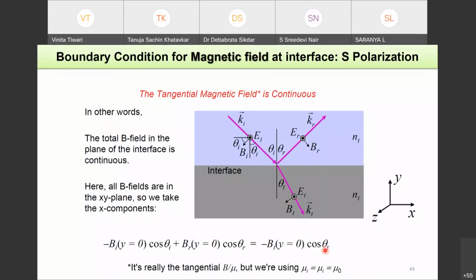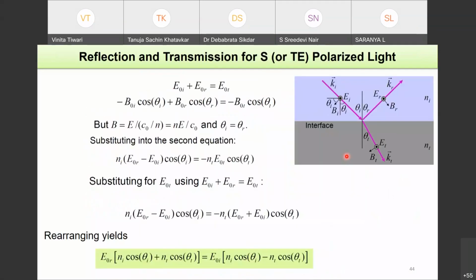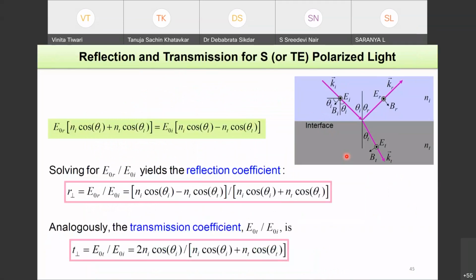And why we are dealing with B, that is the magnetic flux, not the magnetic field, because you can also do it for B by mu. That will be exactly the same, because all the mu's here are 1. We consider all materials as non-magnetic, right? So after you do that, you can use these equations and obtain the ratio of the reflected electric field over the incident electric field, that is your reflection coefficient, and the ratio of the transmitted electric field over the incident electric field, that is your transmission coefficient.